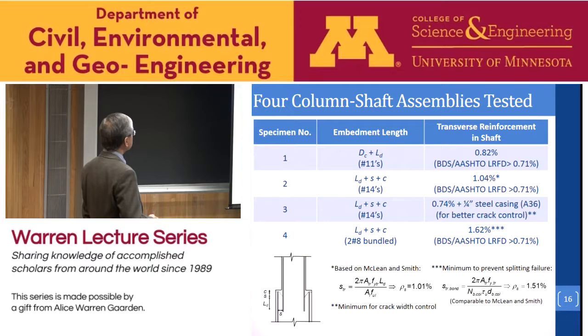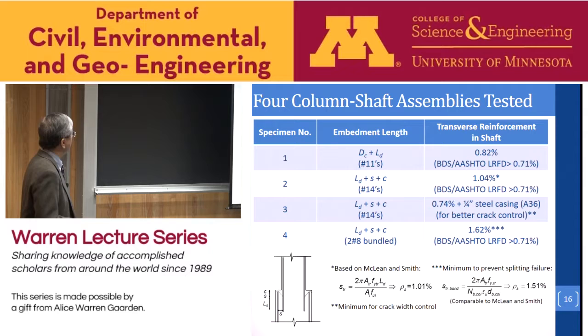So for the variation of the confinement, we use different specifications. One is the minimum required by AASHTO for compression members. The second one we use for a specimen is proposed by McLean and Smith. Actually, this recommendation has currently been adopted by AASHTO. Interestingly, AASHTO uses half of the amount recommended in that study. So we use what is recommended by McLean and Smith.